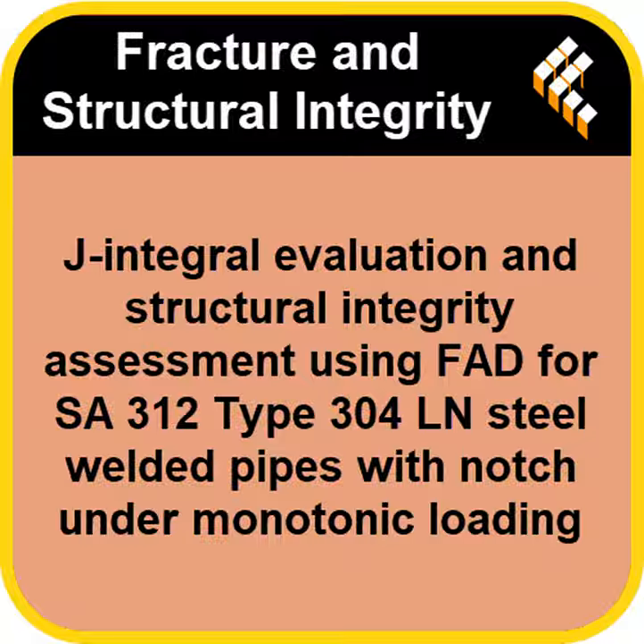Exactly. Welding introduces significant internal stresses. In real-world operation, those residual stresses are a huge factor and add complexity to the assessment. But by removing them through PWHT in the lab, the assessment could focus purely on the effect of the applied load and the material defect itself. It simplifies the model to isolate the core variables we're interested in. So it creates a cleaner experimental environment to determine the fundamental capacity of the pipe with that specific flaw. Precisely. Get the baseline right first.